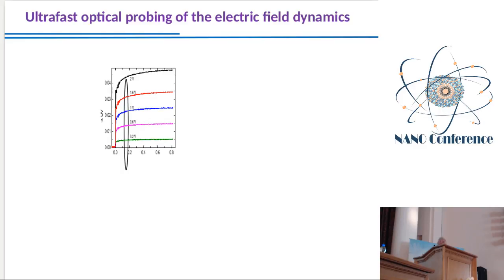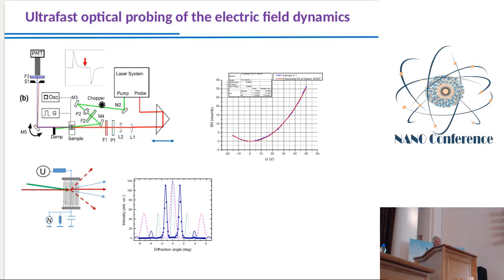This technique is based on the so-called electric field induced second harmonic generation effect. When we use ultra short laser pulses, we can generate second harmonic because of nonlinear processes, but this second harmonic cannot be generated in isotropic materials. So when we apply an electric field, we break this isotropy, we make this material anisotropic, and then when this material becomes anisotropic, second harmonic may be generated.